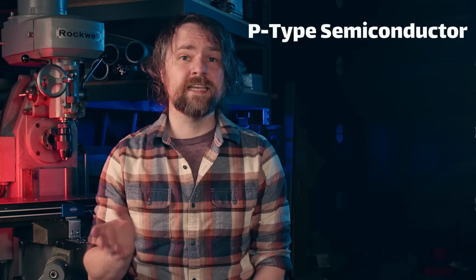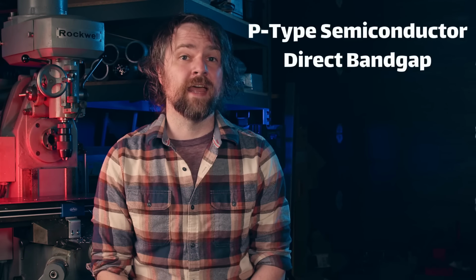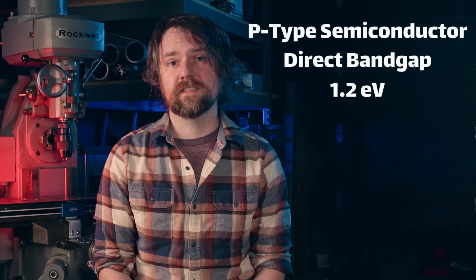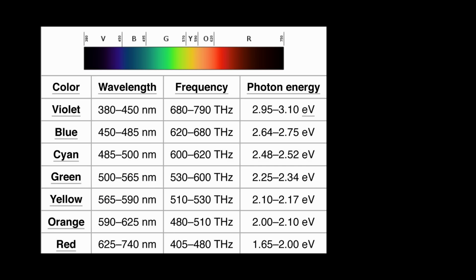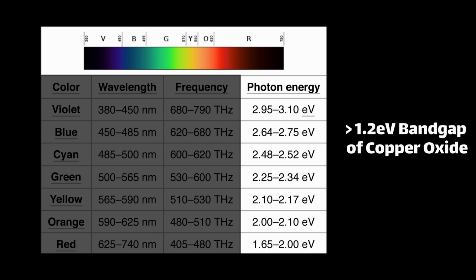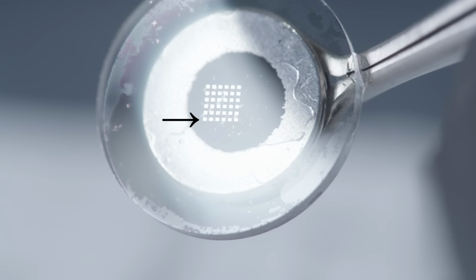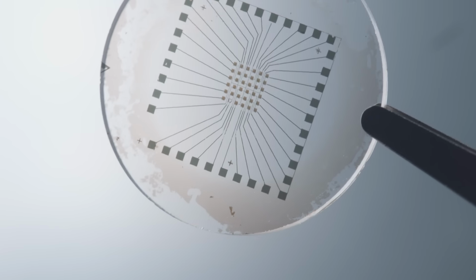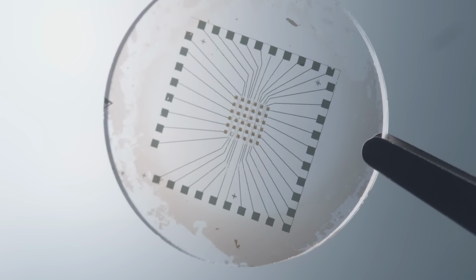Copper oxide is a p-type semiconductor with a direct band gap of 1.2 electron volts. We don't need to get into exactly what that means, but what you should know is that it's sensitive to visible light. Visible light photons have enough energy that they can knock electrons loose inside the material, which in turn generates an electrical current. This is the basis of a photovoltaic cell, basically a solar cell. So copper oxide allows us to build photosensitive sites on a wafer. And if we wire those up with electrodes, we can build a little camera with light-sensitive pixels.